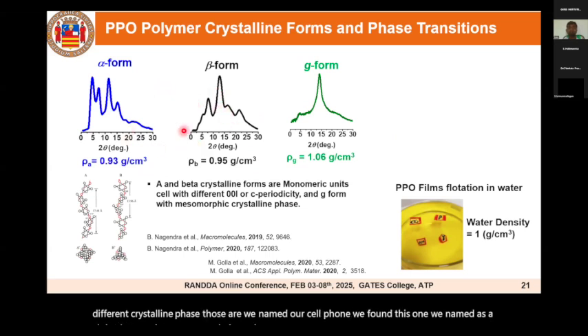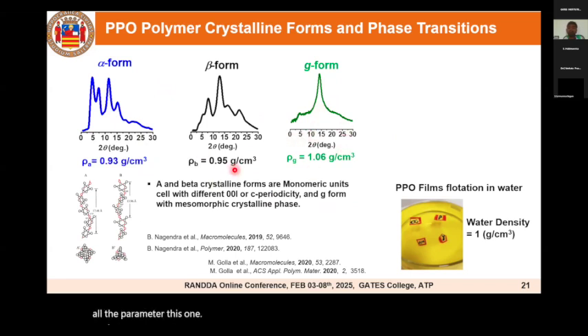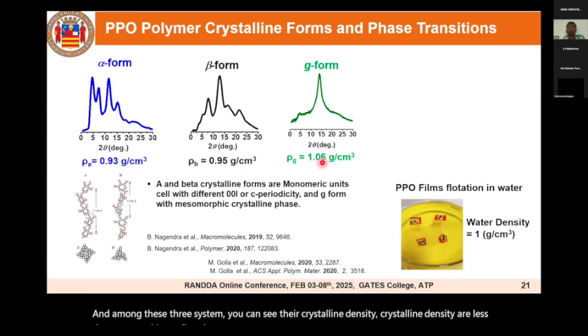These two phases, alpha and beta, have a monoclinic unit cell. They have different chain periodicity. Whereas the third one, the gamma phase, is a mesocrystalline phase. It doesn't have these unit cell parameters. Among these three phases, you can see the crystalline densities of alpha and beta are less than 1. So this confirms that only these two films are nanoporous, whereas the gamma phase has a density more than 1, so it is not a nanoporous crystalline polymer.